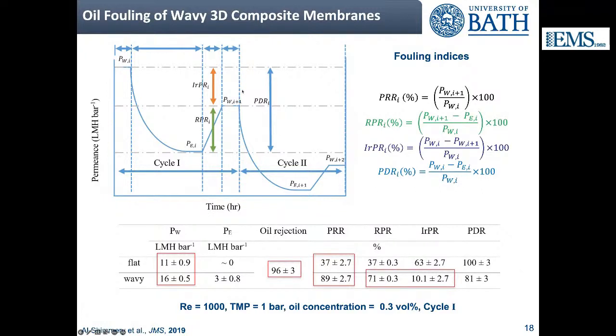So these are the definitions of reversible and irreversible components of fouling, but I want to highlight some data in the table that you find below. First of all, and some of you might have noticed this from the plots in the previous slide, the wavy membrane has a higher permeance in LMH per bar than the flat membrane, even though they have the exact same footprint. So the membranes are 47 millimeter in diameter and fit in a standard cross-flow cell. The reason for the higher permeance of the wavy membrane is that because it is wavy, it actually has a higher surface area within the same footprint. So this is an added bonus, if you want, of using 3D printed structures, in that you're adding a third dimension to a membrane, which is otherwise flat or 2D.